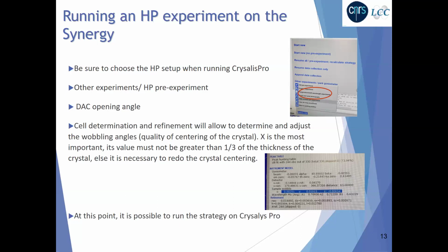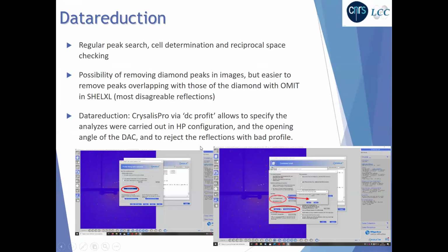Once you are happy with that, then it's possible to run the strategy on CrysAlisPro in a quite regular way, as you will do for regular experiments. Once the data collection is finished, it is recommended to do regular peak search, cell determination, and to check your reciprocal space. It is possible to remove the diamond peaks, the spurious peaks, in the images directly. But in our opinion, it is easier to deal with those spurious peaks once you are refining your structure. For example, when you are using SHELXL, by checking the most disagreeable reflections and by removing the worst with the OMIT command.